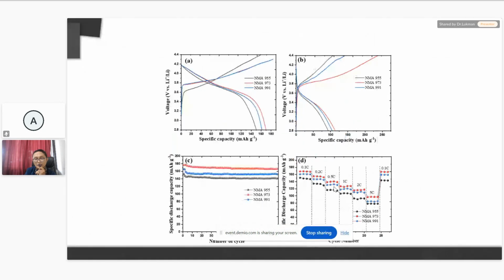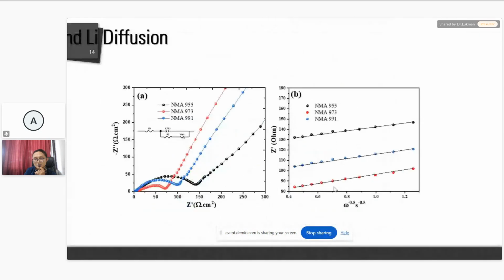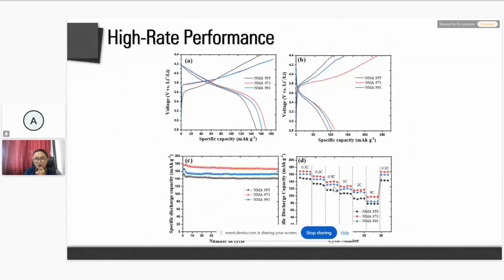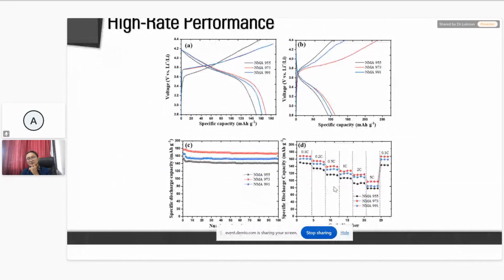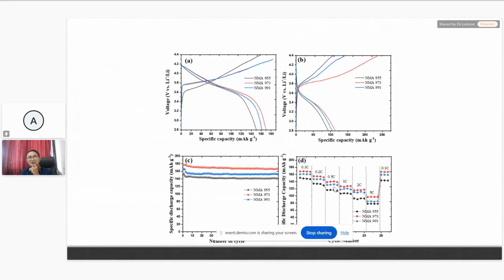And we are now going up to the electrochemical performance of our control. This is the first: A is a typical charge discharge curve for NMA here, for the range from 2.8 to 4.4 volt, and we use 0.1 C. We observe that there is a slope at around 3.8 for the working window for this kind of NMA.